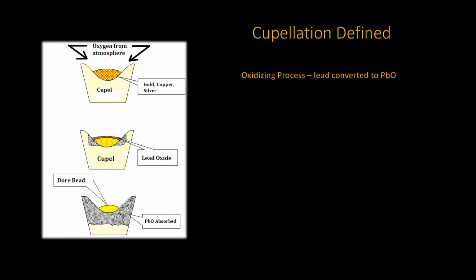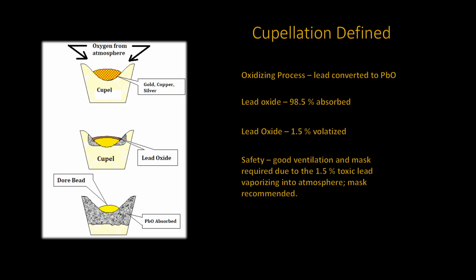Cupellation is an oxidation process with a slight twist. Oxygen from the atmosphere will be allowed to enter the muffle furnace. The lead making up the lead button is thus oxidized into litharge, which in turn 98.5% will be absorbed into the porous container referred to as a cupel, and 1.5% will be volatilized, hence the need for some personal protective gear and good ventilation. What should remain in the bottom of the cupel is what is known as a doré bead, which is a metallic alloy of your precious metals and noble metals, that is, if there are any.